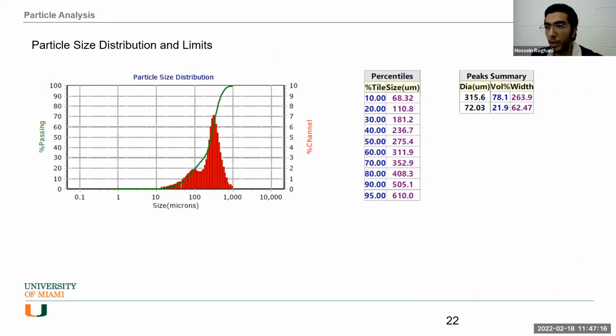Here there's another thing I'm going to mention, the particle size distribution and the limits. For that we have another device, which we call Microtrac, the particle size analyzer. It can help us characterize and measure the particle size limits and the distribution. For this test, first we have a fiber content test for the rebars. We put a small piece of the rebar, for example 1 inch, in the oven and burn out the resin, and at the end you have just the sand coat, if the rebar is sand coated, and the fibers. You can easily take out the fibers, and at the end you have just the sand particles. Using this particle analyzer, we can measure all those particles.